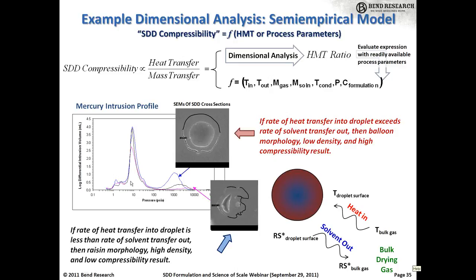We also developed a mercury intrusion test to quantify the interior void volume of these particles. And we won't talk too much about this test just due to time, but it turns out that this test correlates nicely with the tablet manufacturing process parameters. So that worked well for predicting how it might behave in downstream manufacturing.